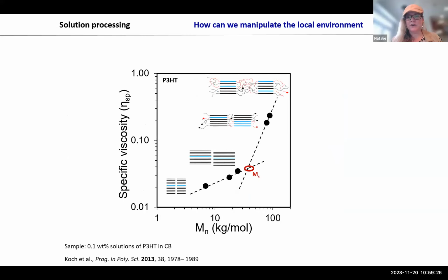And let me see, can you see my slides again? Yes. Voila. And that has really to do with the entanglements. And it's a pity that my graphics got lost, but once you go from the critical molecular weight to here, in these molecular weight regimes, you really have a lot of entanglements. So if you would melt, actually that would do the opposite effect. The P3HT would be really entangled with itself, the PVDF would be entangled with itself, and they will never interact because there's no driving force, neither enthalpic nor entropic. They're already very disordered, entropy is high, there's no driving force for them to actually mix.